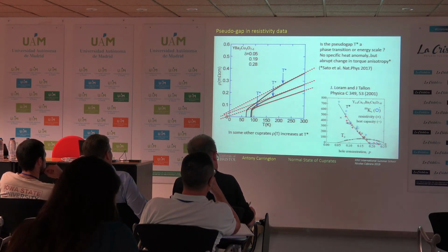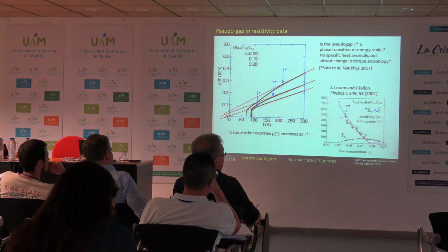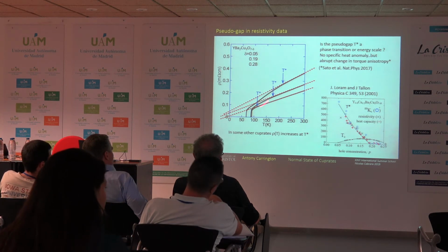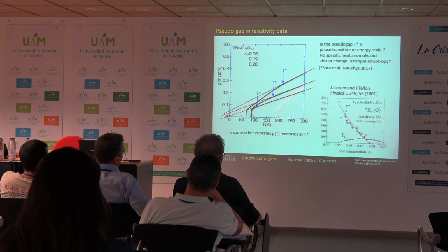Whereas as the temperature becomes low, then the occupied density of states is focused more around the Fermi level, and so you see more of this depression. So one of the things against this being an actual phase transition is that people have looked very, very carefully, and there is no heat capacity anomaly as you go through this point. However, very recently, Yuji Matsuda's group has identified a change in a thermodynamic quantity, namely the anisotropy of the in-plane torque, which does seem to occur at a similar temperature, but whether or not that truly marks the pseudo-gap or is a consequence of the pseudo-gap forming, I think is still an open question.